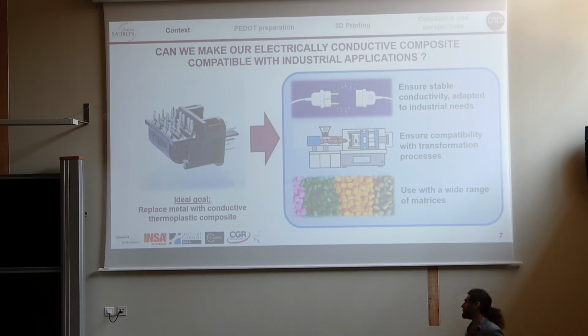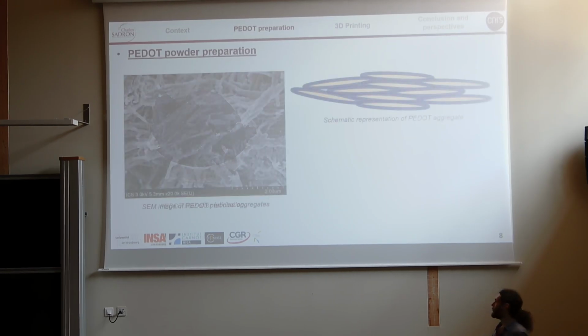to verify a few points, such as the stability of the conductivity during operation, the compatibility with transformation processes, and so on. So first, to ensure a good stability of the conductivity in the composite, I decided to study the grinding methods of the PEDOT. Just after the synthesis and the drying, you obtain big chunks of PEDOT. And when you zoom and observe them at the microscope, you have those fibrillar particles, but you can see that they are very much aggregated.